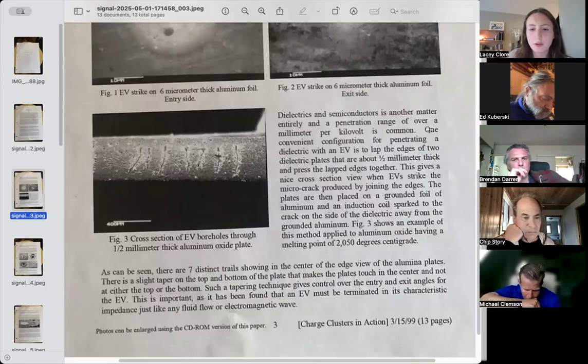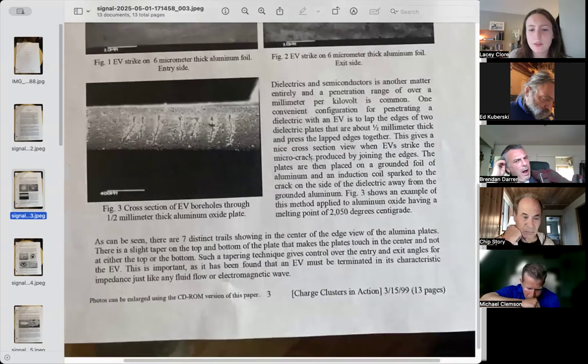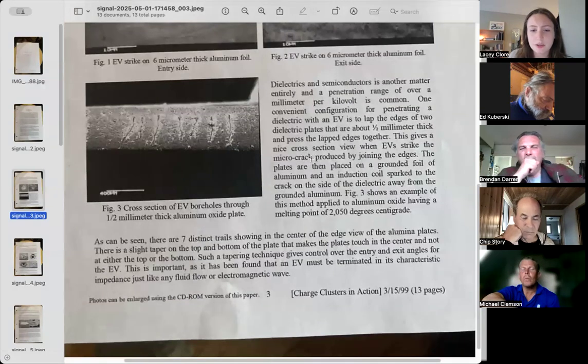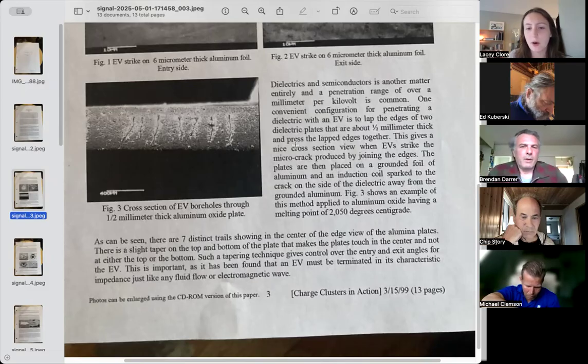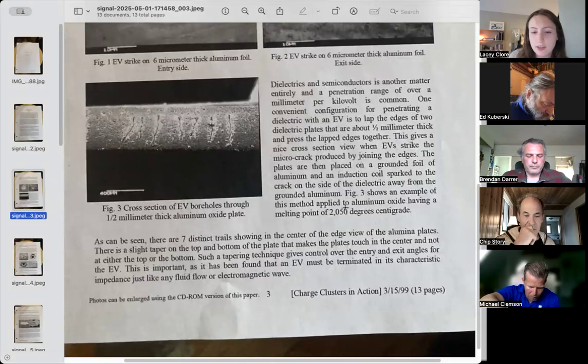Kilovolt is common. One convenient configuration for penetrating a dielectric with an EV is to lap the edges of two dielectric plates that are about a half millimeter thick and press the lapped edges together. This gives a nice cross-section view when the EV strikes the micro-crack produced by joining the edges. The plates are then placed on a grounded foil of aluminum and an induction coil sparked to the crack on the side of the dielectric away from the grounded aluminum.